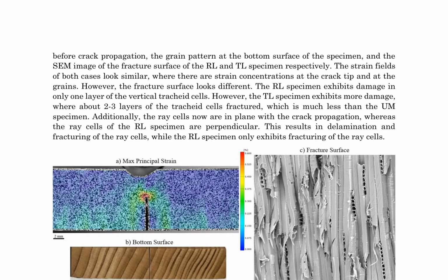In the context of wood fracture mechanics, a comparative analysis was conducted between radial-longitudinal (RL) and tangential-longitudinal (TL) wood specimens, focusing on their grain patterns and fracture surfaces. Digital image correlation (DIC) was employed to measure the strain fields preceding crack propagation. The resulting strain fields for both RL and TL specimens exhibited similar characteristics, with strain concentrations at the crack tip and grain boundaries. However, the fracture surfaces of the 2 specimens differed significantly.